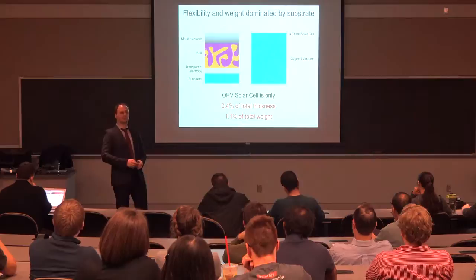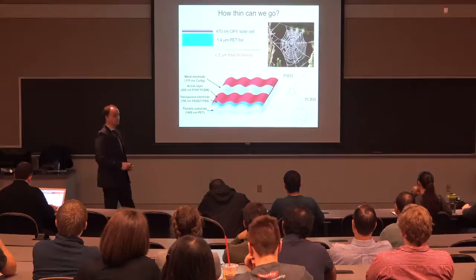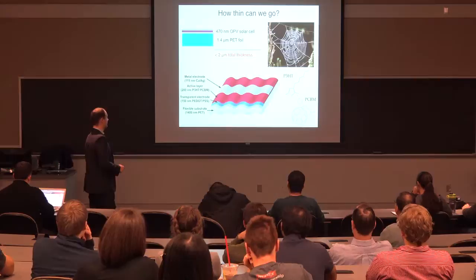Now obviously you can scale down the substrate. People haven't done it until we did it in 2012 to that extreme. So what we did is we used a commercial foil, 1.4 micron PET. Why commercial? Well, if it's commercial, you can buy it, you can scale it up, that's good. And on this, we made a solar cell less than a micron and have devices altogether less than 2 microns. So what's 2 microns? That's about the same as the thickness of a spider silk strand.